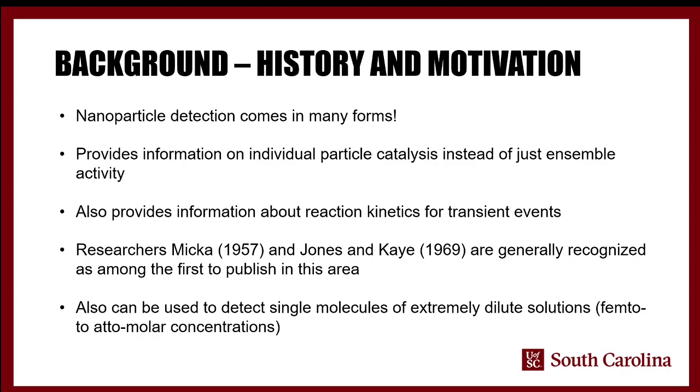But you could come back here and do the single particle catalysis and find that any particles that are less than a certain diameter will carry out the reaction, but will then deactivate for some reason. And so once you know that, you can start trying to figure out what the deactivation mechanism is, and if it's something that you can fix, you fix it, and if it's not, then you try and make sure that your catalysts are larger than that threshold size, and then you don't have to worry about it.